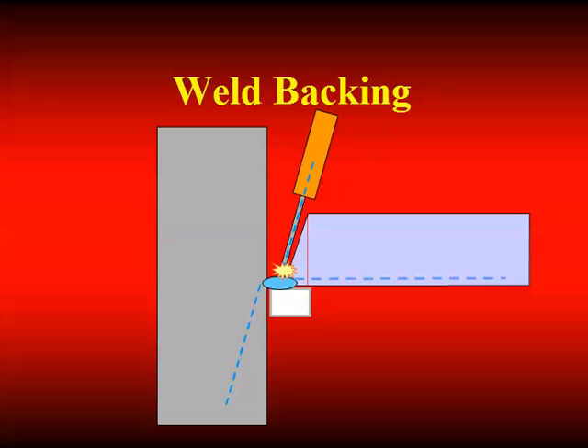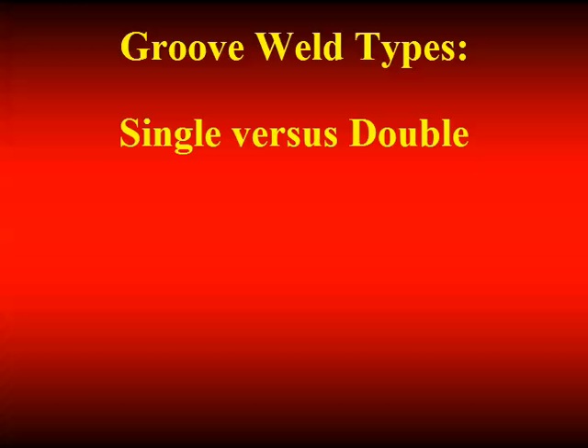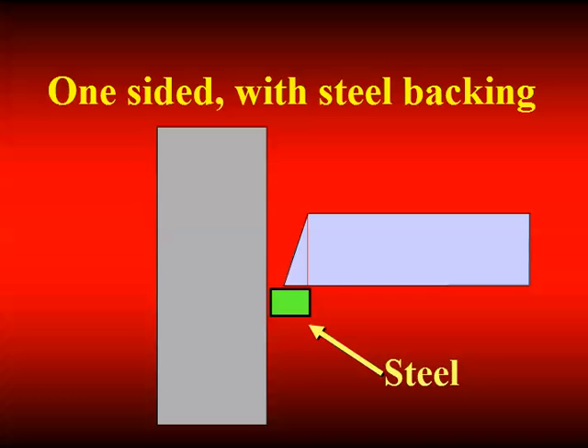Let's talk about single versus double-sided joints. In general, we use steel backing if we have a single-sided joint. Now that's the pre-qualified joint details, and there's one or two exceptions where we weld from one side without steel backing, but most of the time, certainly when we get to heavier material, our pre-qualified joint details use steel backing. Copper and ceramic are not pre-qualified. Only the use of steel backing is pre-qualified.